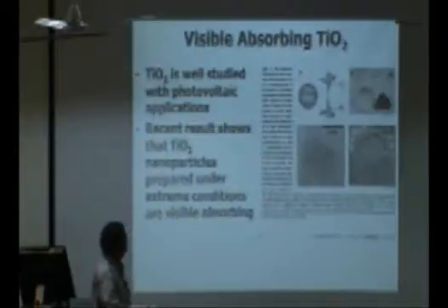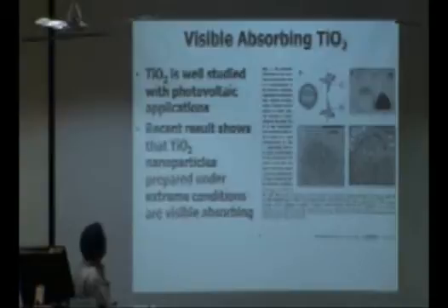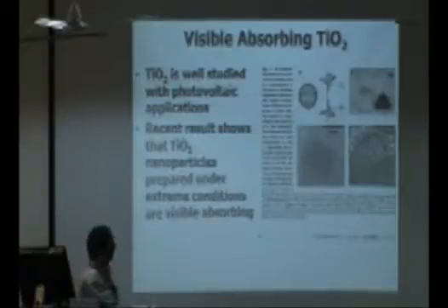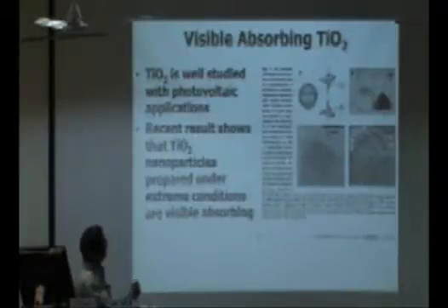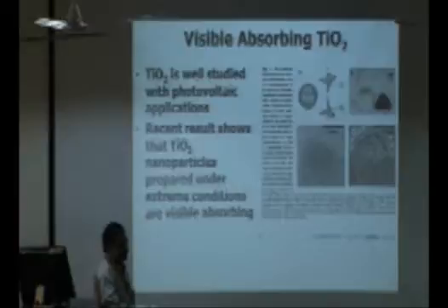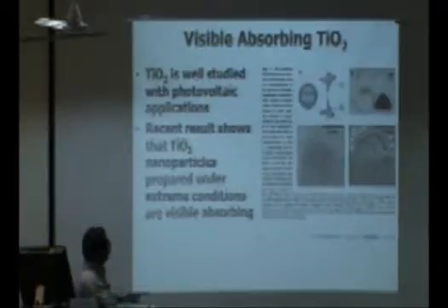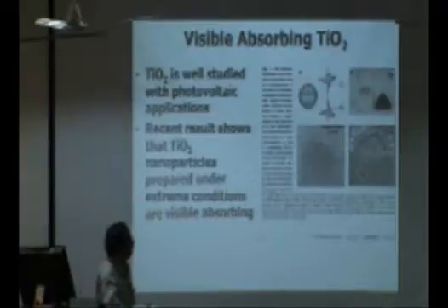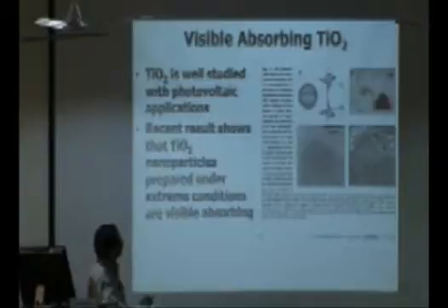As an offshoot of that problem, we have visible absorbing TiO2 films. TiO2 is well studied with a lot of photovoltaic applications. In 2011 there was one report which showed that under extreme conditions, you can have TiO2 nanoparticles made at extremely high pressure and excess hydrogen conditions, and you can get these dark or black TiO2, unlike the traditional TiO2 which is white in color.